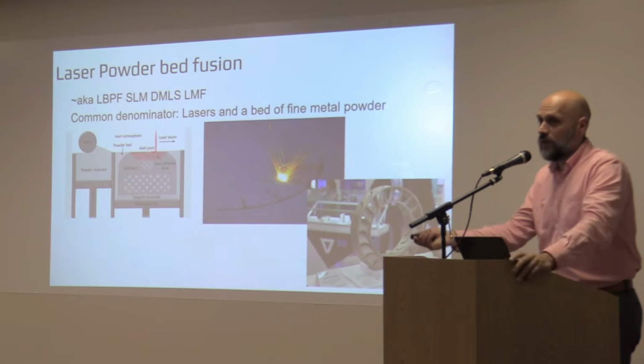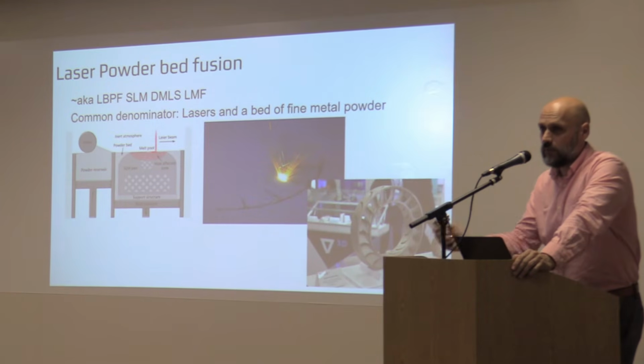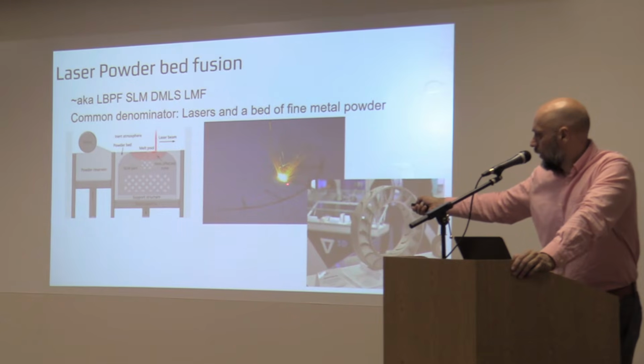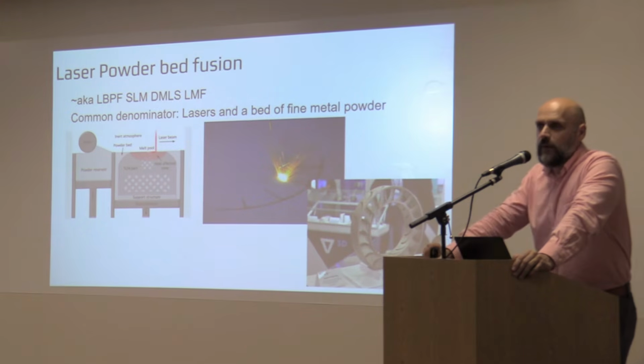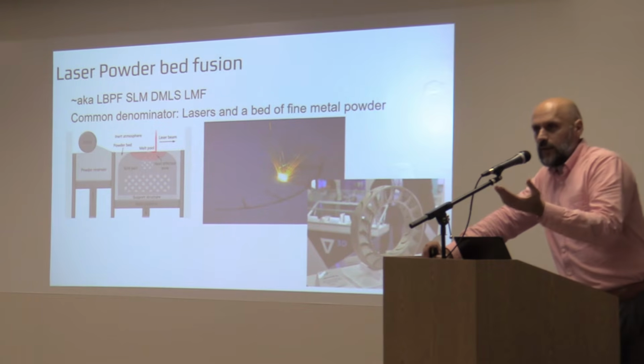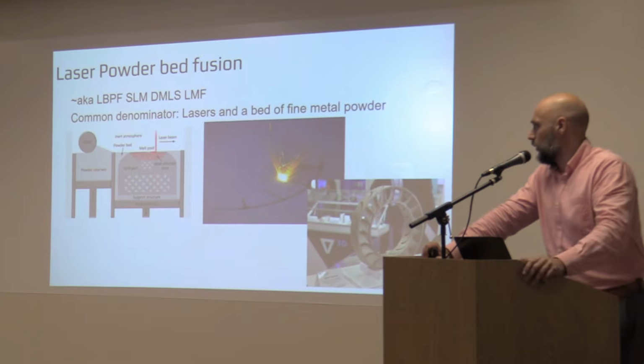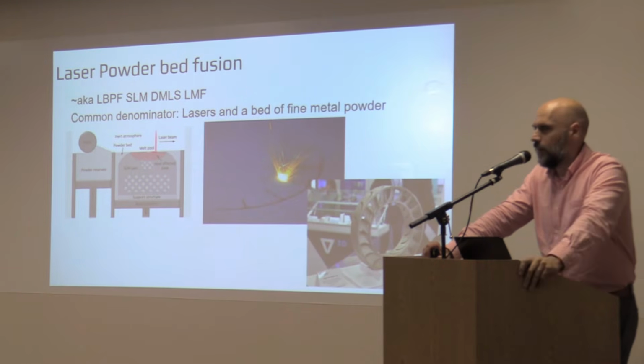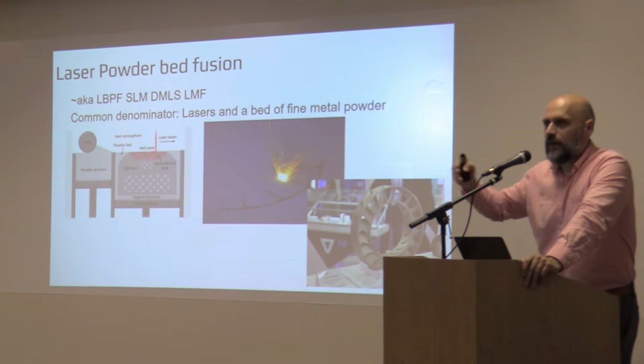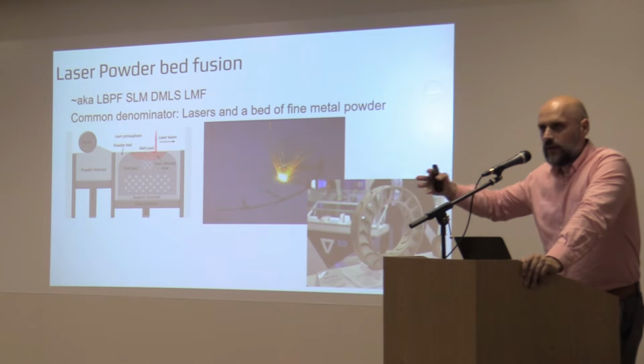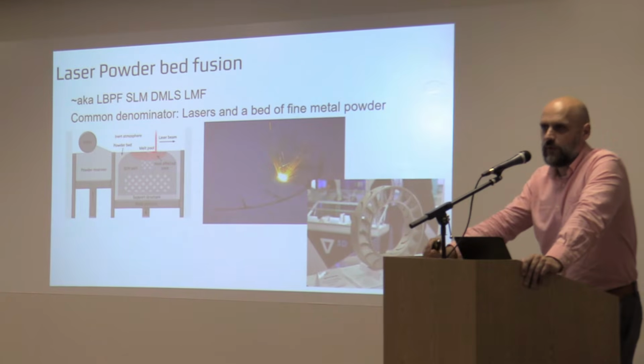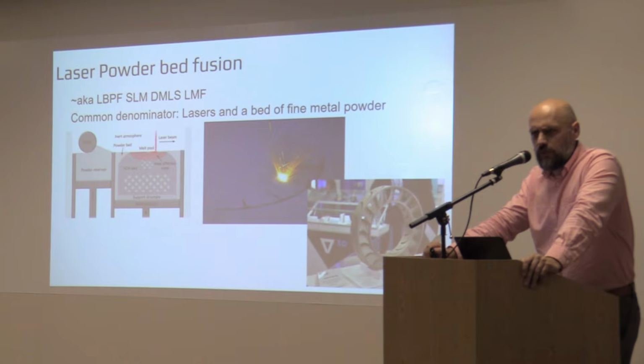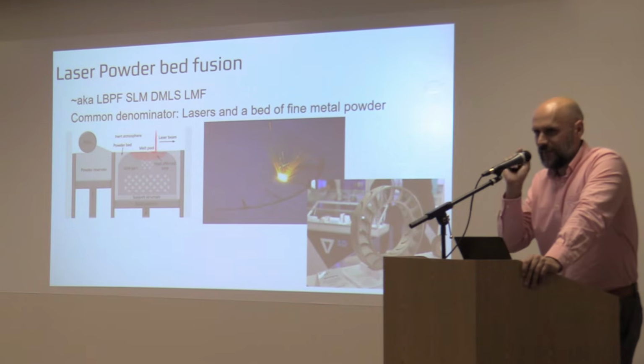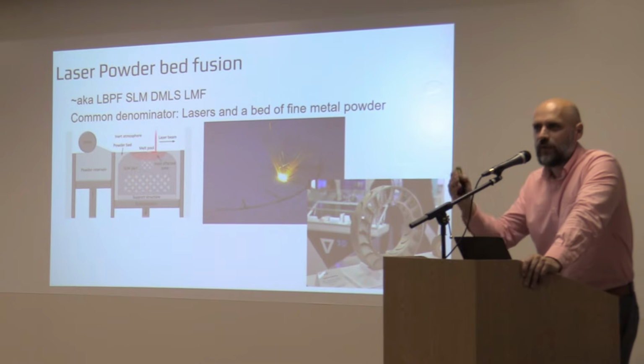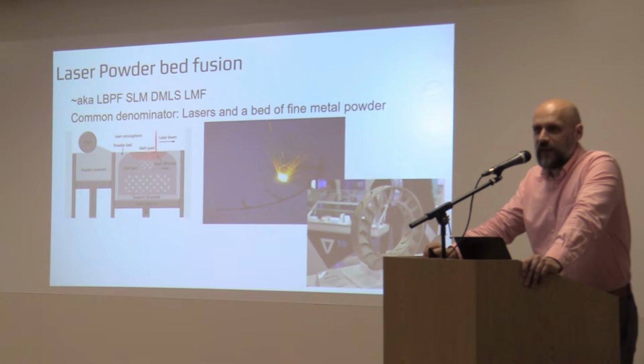You have to melt just enough to instantly solidify it. When I say instantly, the solidification rate in this thing is about 10,000 degrees a second, right? You see here, the laser is here melting. That's already solid, right? It's just instant. Let's say the melt pool is about 70 micrometers. Think about it, a crater of 70 micrometers of molten metal. And you never want to build more than 3 times the diameter as you go, because the moment you do that, it balls up. Surface tension takes over. So you always want to cool down faster. I think Ohnesorge was the guy that discovered how much liquid you can have as a worm before it becomes a ball. It's about 3 times the diameter. So I found out about it experimentally before I read the theory behind it.